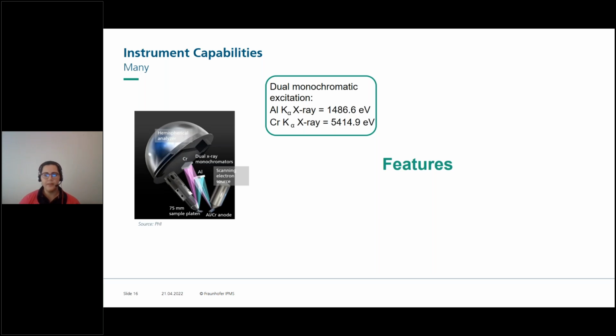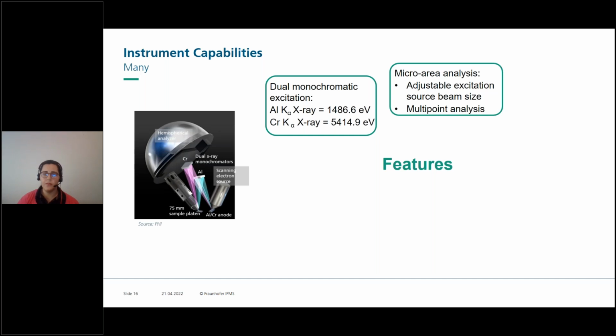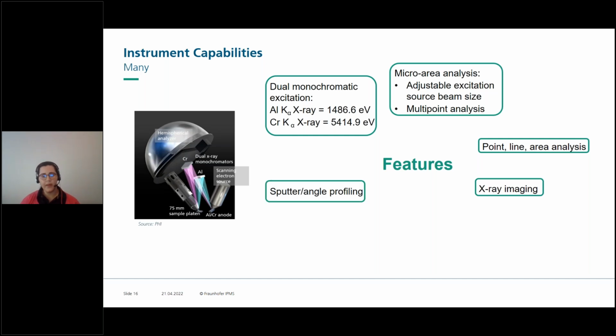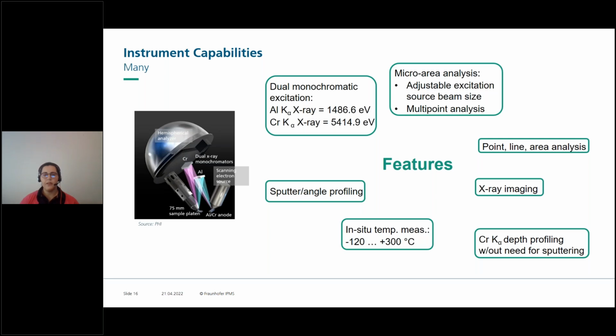We have a shutter that automatically switches between the sources during measurement, which makes measurement quite fast. We also have the possibility to do micro-area analysis, where we can adjust the excitation source beam size and therefore multi-point analysis. We can do point, line, and area analysis. We also can do X-ray imaging, sputter and angle profiling, and we can use Chromium Kα for depth profiling without the need for sputtering. And we can also do in-situ temperature measurements ranging from -120 to +300 degrees Celsius.